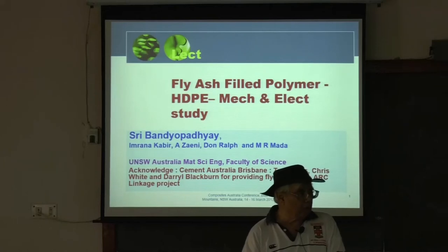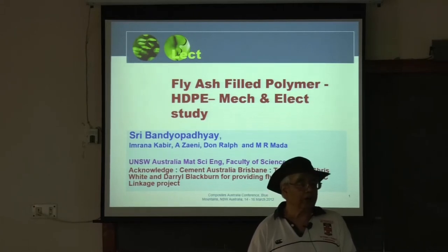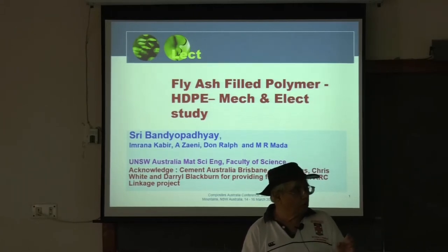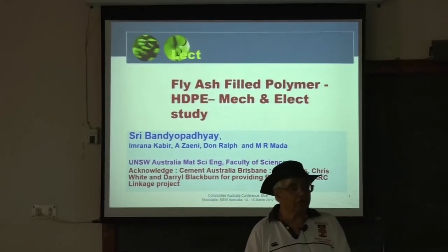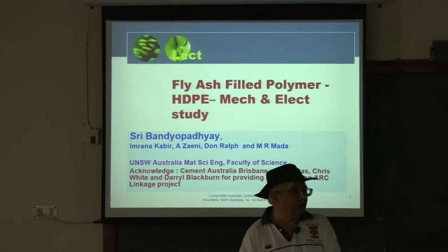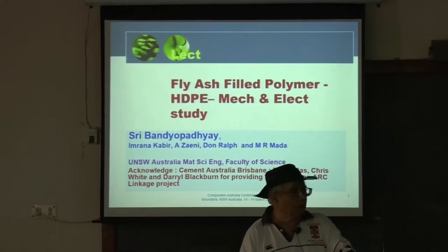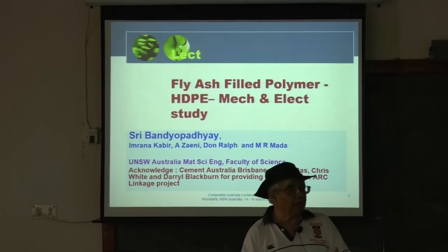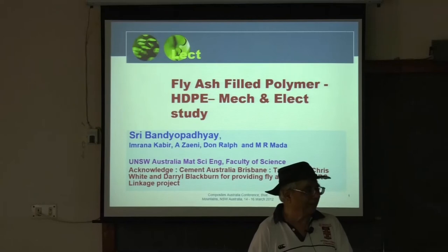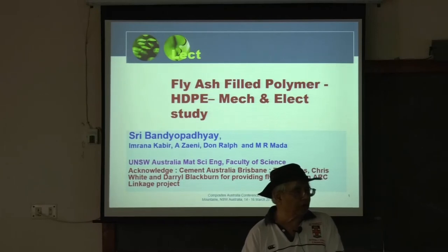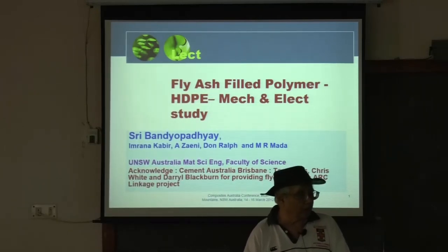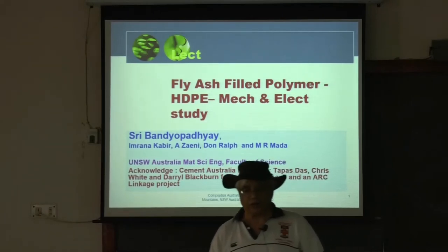There are two ways of getting better electrical properties. One is if you have higher LOI, but higher LOI can also cause other problems. So what we did was put the standard lower LOI fly ash, but then made different composites with more percentage of fly ash. That way the ceramic or cementitious properties of the fly ash do not change, but if you have more and more fly ash, the polymer matrix sees more and more carbon.